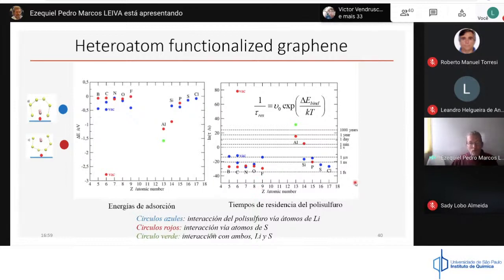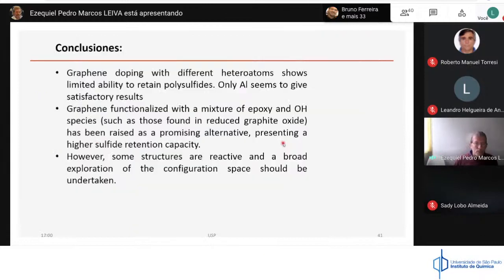And as I told you, the only case where you have a reasonable retention time, and when I say reasonable, I mean a day or more, for the polysulfide on the surface is in the case of aluminum. We have also considered another type of surface, like oxidized graphite surfaces. I don't have the time to speak on that now. But we can conclude that graphene with different heteroatoms has a limited ability to retain polysulfides. Only aluminum seems to give a satisfactory result.